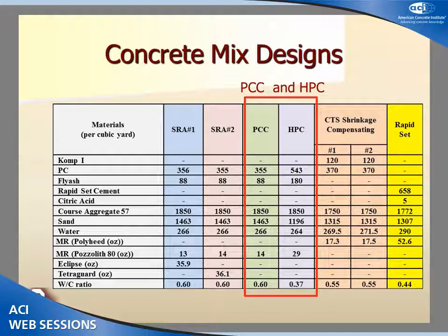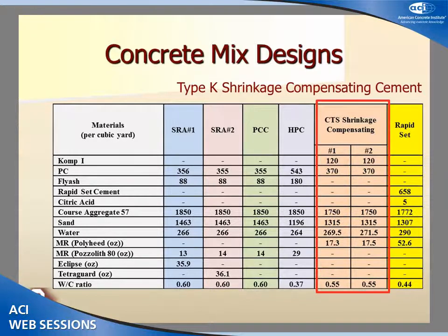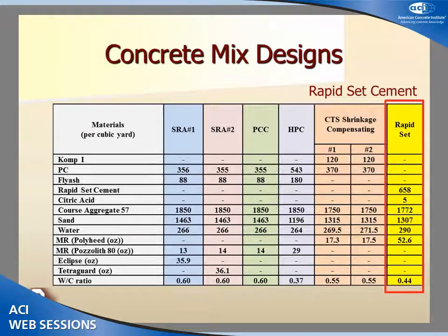So 2 of the slab specimens were made with Portland cement concrete and high-performance cement concrete or high-restraint concrete. And 2 of the slab specimens were made with type K shrinkage-compensating concrete, and also one of the slab specimens was made with rapid set, which gets its strength at early age.